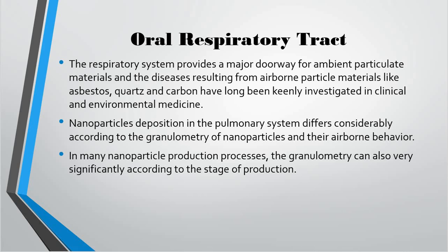In the alveolar region, the macrophages will take up the insoluble particles by phagocytosis. However, the effectiveness of phagocytosis is strongly dependent on nanoparticle shape and size. Several studies have proved that polyethylene nanoparticles of general nanoscale size deposited in the alveolar region are not phagocytosed efficiently by the macrophages. However, the macrophages are especially efficient for coarser particles in the 1 to 3 micrometer range.